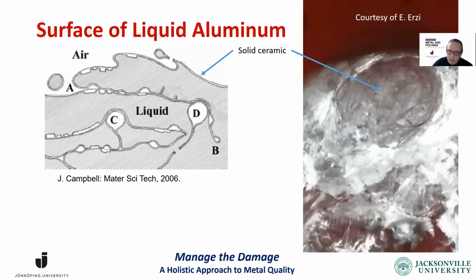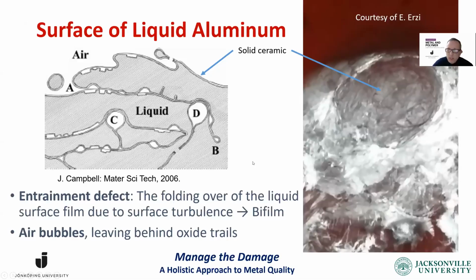And then this ceramic gets folded on itself, and those two films that touch each other have no bonding between them. There's some air entrained as well. So the result is what you see schematically on the left. So we have an entrainment defect, and it's called a bifilm because there are two films touching each other. And there are air bubbles. Most of the time they leave behind oxide trails because the air inside has oxygen, so it reacts immediately with the aluminum, and then with nitrogen it leaves trails of ceramic.